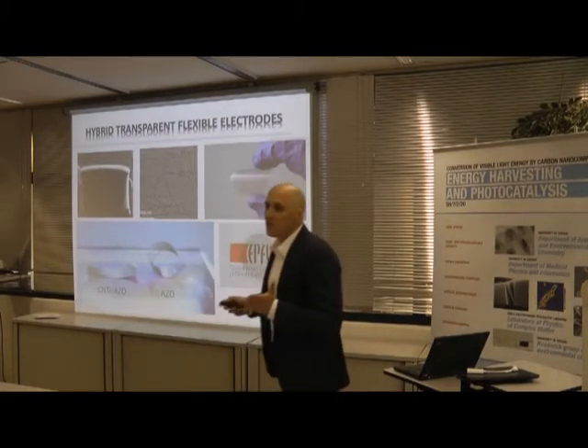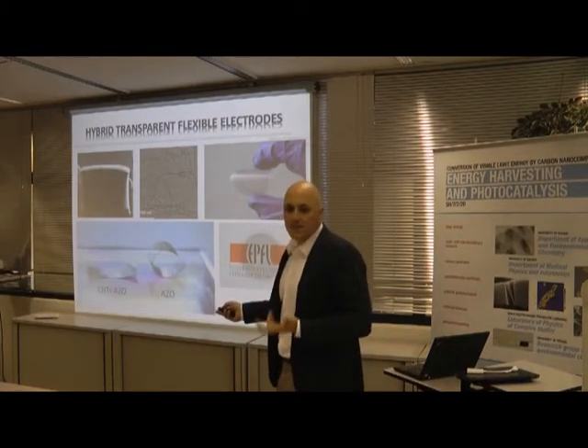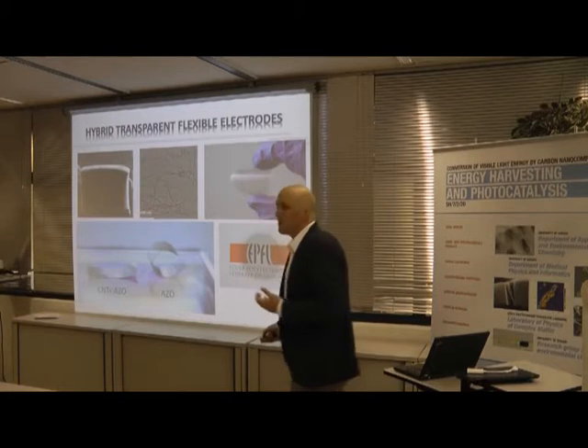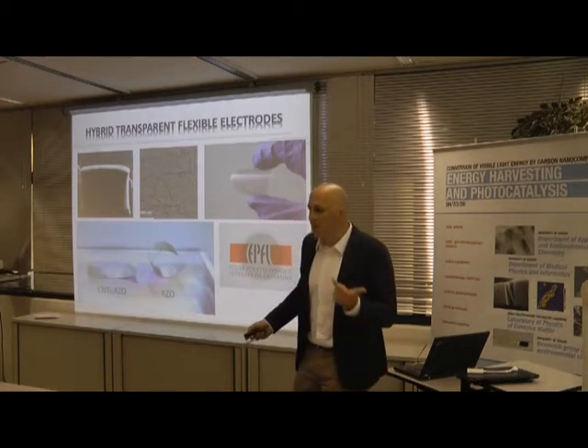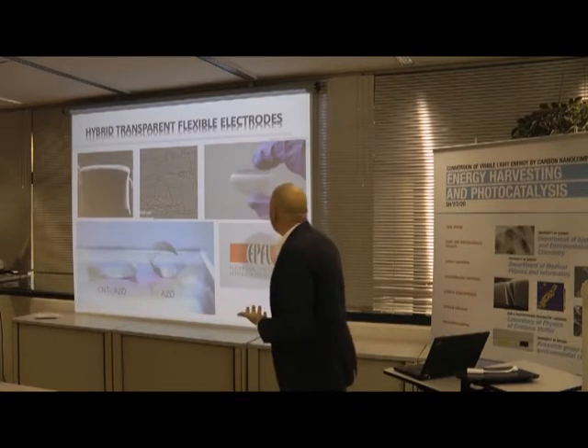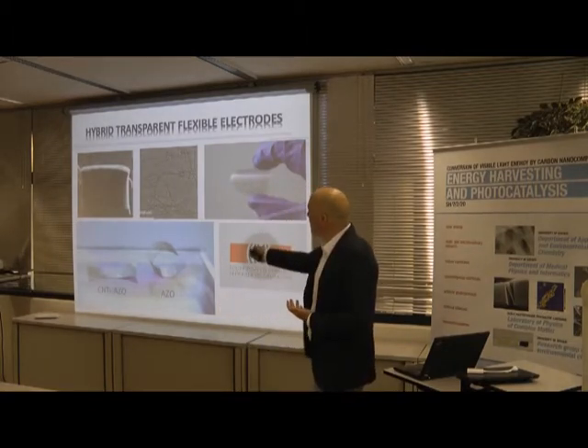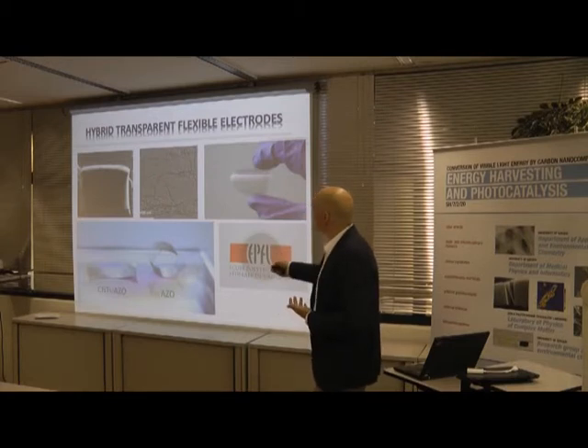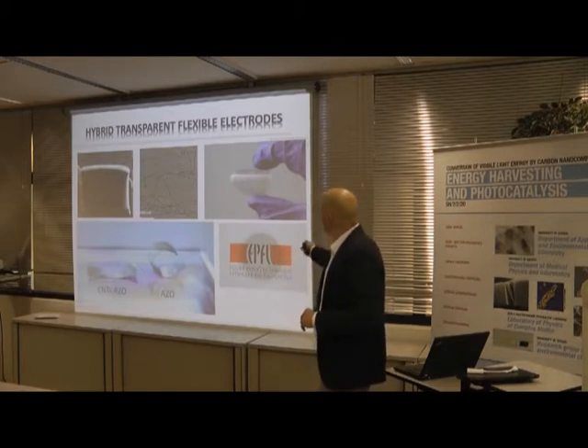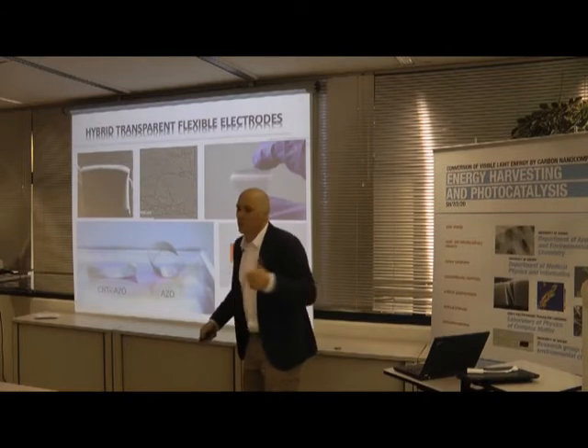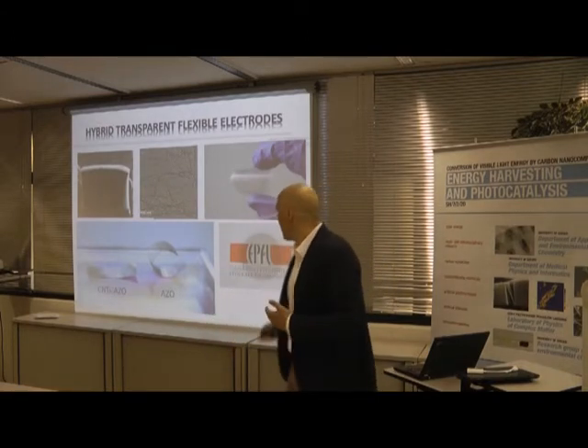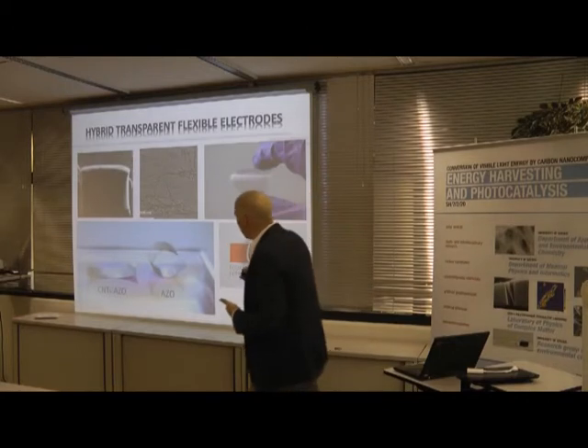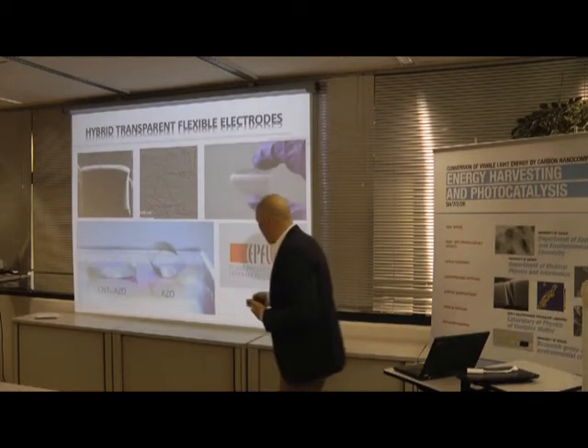If you want to have a flexible solar cell, you would need flexible glass, but flexible glass doesn't really exist. So that's why you need alternative materials. And carbon nanotubes and graphene are among the promising candidates to make such a film. Here we use extremely long multiwall carbon nanotubes, a carbon nanotube forest. We detached it from the substrate, suspended it, and printed the suspension on a polymer film. So now you have this thin layer which is transparent and a good conductor. And we deposited this ceramic, like ITO or FTO, the conductive glass, on the surface. Here is without the carbon nanotube scaffold, and this picture is with the carbon nanotube scaffold.